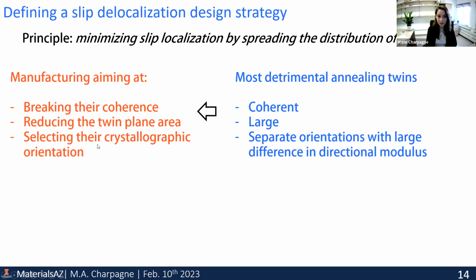About the third topic, I just want to mention that all the materials that we're dealing with are texture-free, so this is pretty much hopeless. And we decided not to investigate this because we cannot really control the texture of the material so that we wouldn't have large differences in directional modulus across the twins. Also because we have 4 twin variants per orientation, so this is, I want to say, almost impossible to do. However, we focused on trying to break the coherency of the annealing twins and reducing their twin plane area.